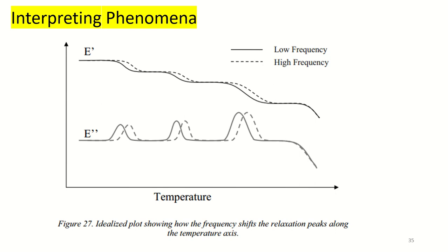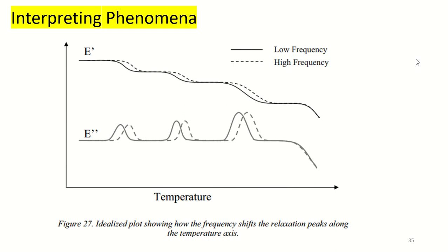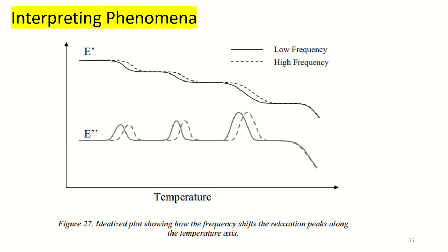It is generally accepted that glass transition is due to large scale main chain molecular movements. Other relaxations may happen at temperatures below glass transitions. They are caused by the motions of smaller segments within the main chain or pendant groups and may correlate to important properties such as toughness.